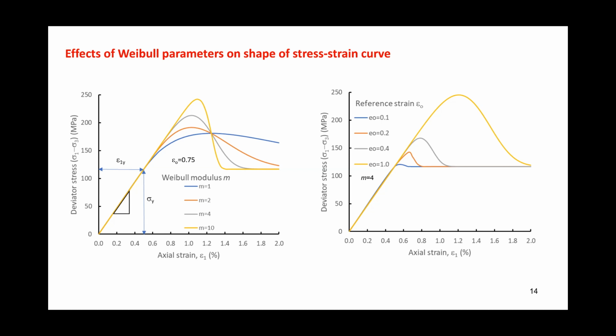As you can see, as you increase M, from 1 to 10, increasing M increases the shear strength. The material is stronger. Also, it shows a more distinct strain softening, so there is a more sudden drop in the shear stress towards a residual stress. The reference strain, this is for M equal to 4.